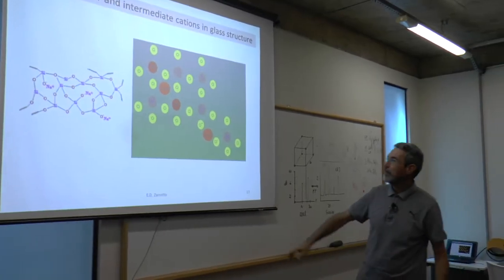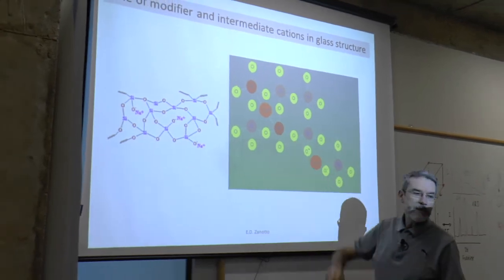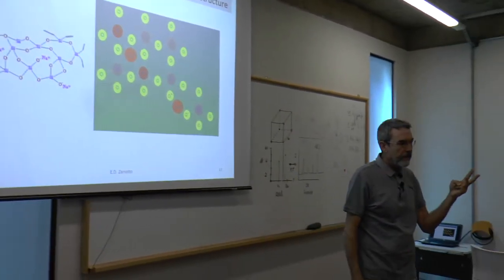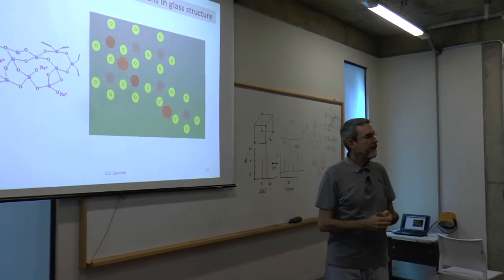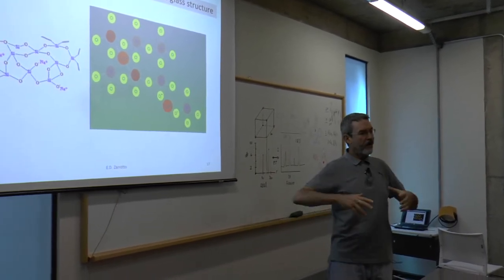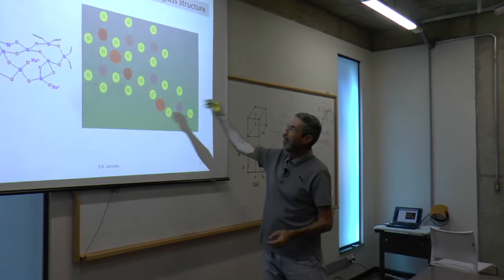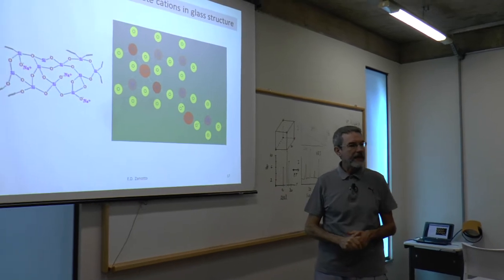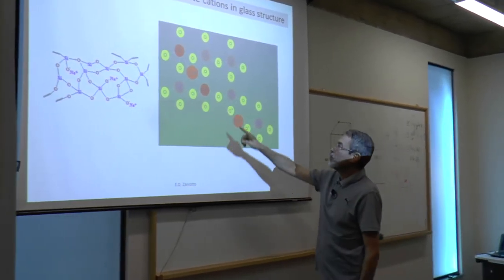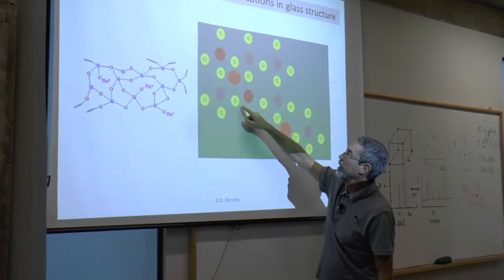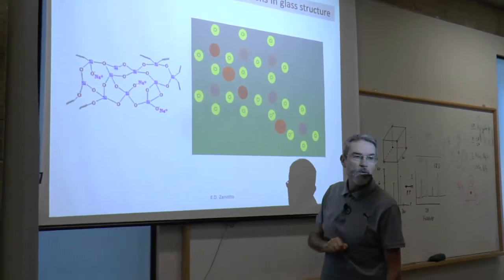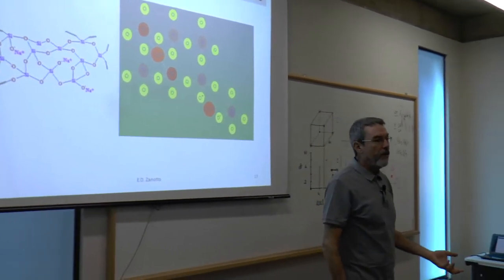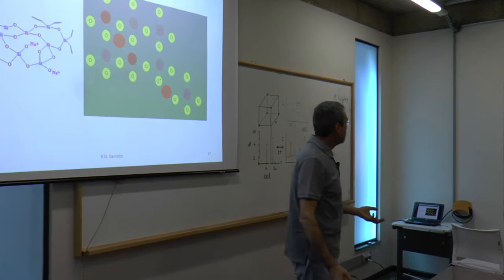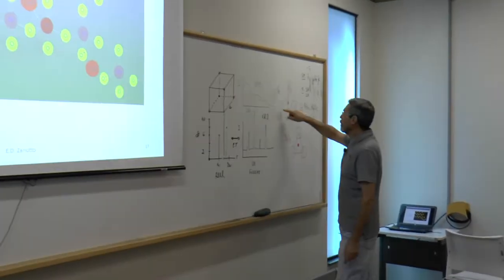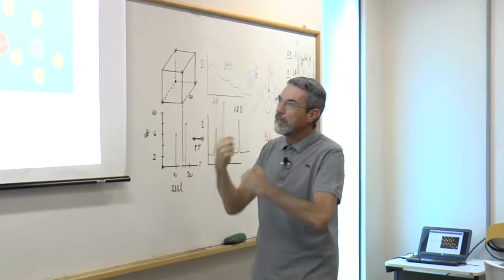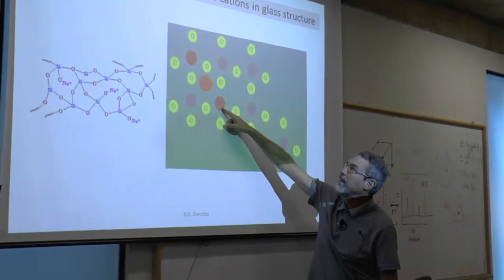Well, it's very interesting because aluminum has a valence of 3. But for some wishes of nature, when we add alumina to silicate glasses, aluminum takes a coordination of 4. The aluminum, 1, 2, 3, 4 oxygens. So it recovers non-bridging oxygen. It has the opposite effect. So it will recover some of non-bridging oxygen because it takes one more oxygen to form strong links.